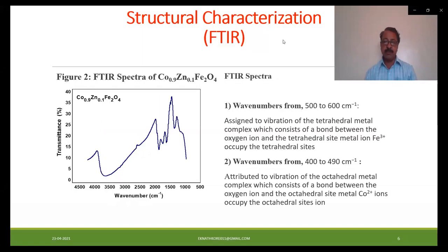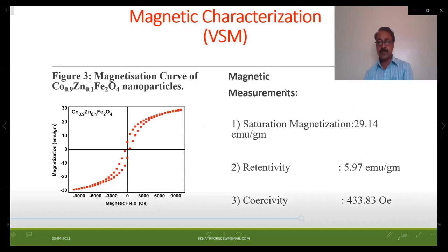Further, the FTIR shows that the higher frequency absorption band lies from 500 to 600 cm^-1, assigned to vibration of the tetrahedral metal complex, which consists of bond between the oxygen ion and the tetrahedral site metal ion Fe3+. And the lower frequency absorption band corresponds to 400 to 490 cm^-1, attributed to vibration of the octahedral metal complex, which consists of bond between an oxygen ion and octahedral site metal ion Co2+.